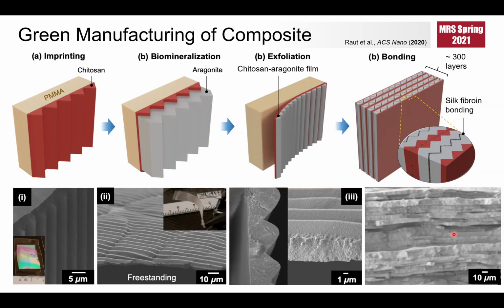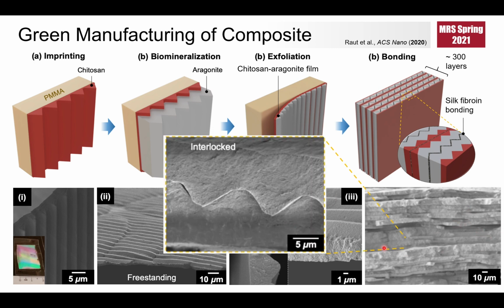After the synthesis of the wavy mineral platelets, these platelets supported on chitosan films are stacked and infused with silk fibroin. Silk fibroin has been previously shown to bond chitosan aragonite composites together. While stacking, the wavy sides of each film are made to face each other. As a result, the wavy platelets eventually get interlocked after the silk fibroin dries and bonds the layers together. By this process, the interlocked composites were fabricated. The same process was repeated for control samples comprising planar mineral platelets as well.